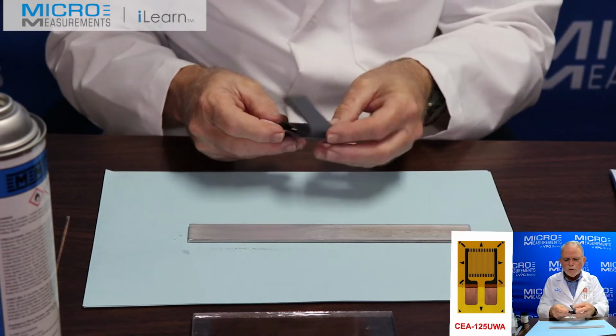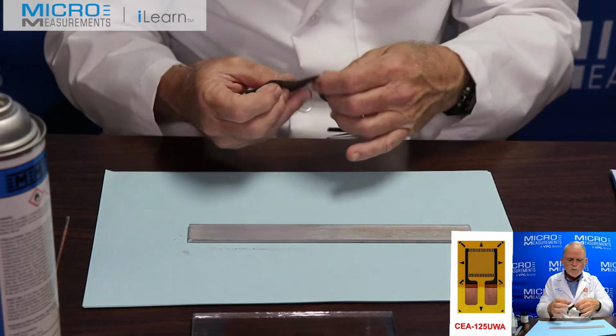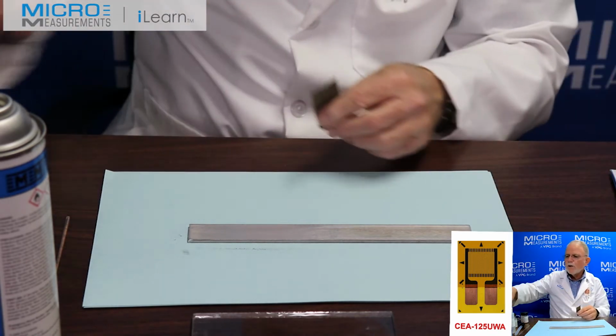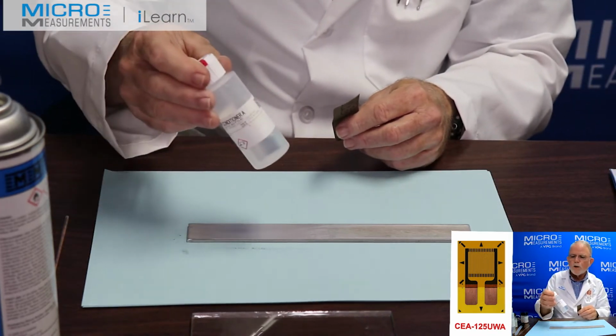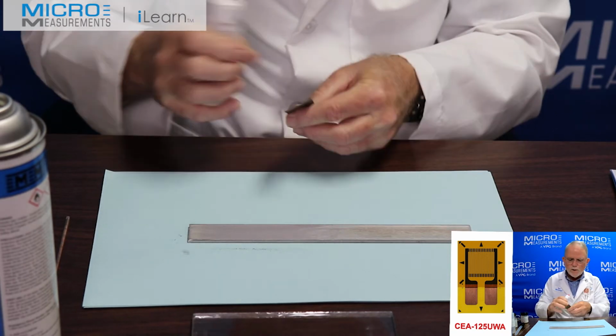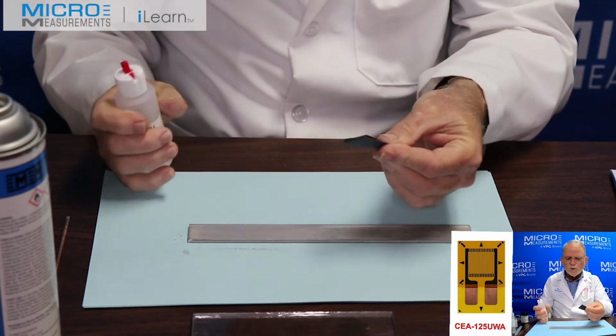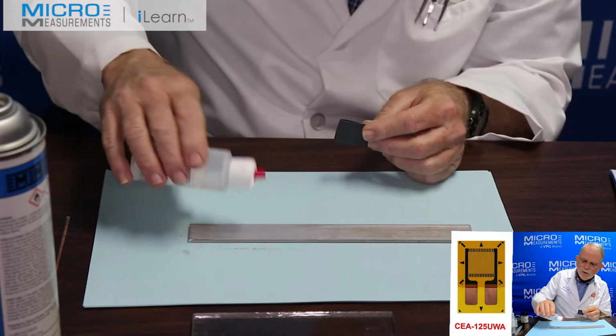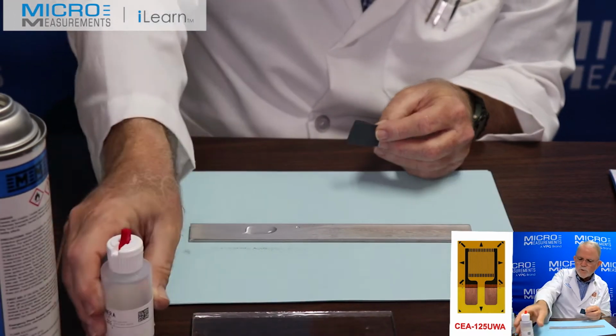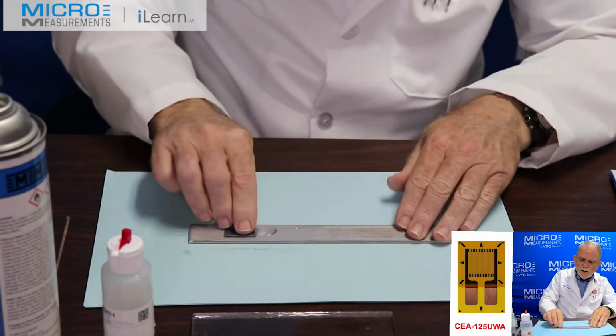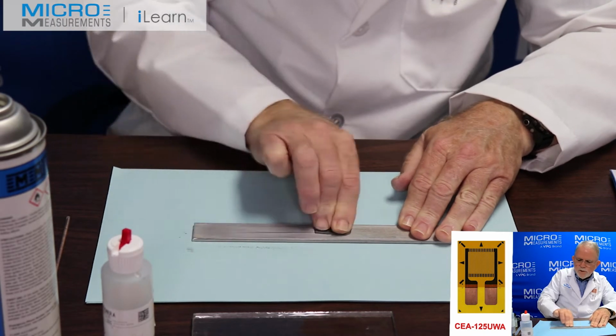The next step, we'll again use the 320 grit silicon carbide abrasive paper, the SCP-2, and the conditioner A, the mild phosphoric acid solution. I'm going to again fold a piece of the silicon carbide abrasive paper into half, flood the surface with the conditioner A, and then wet abrade, 10 or 12 strokes.